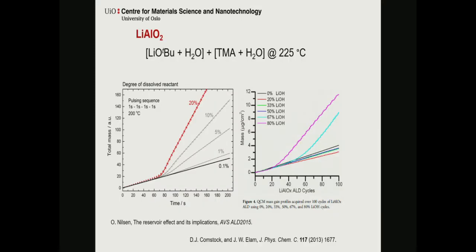We've seen such effects, particularly when we use lithium as a precursor. That's for the battery material, because lithium is so highly mobile, so it seeps in and out of the film. If you then allow different concentrations in your film and then simulate the QCM signal, then it looks as normal, but you build up spikes at a period before it suddenly takes off.